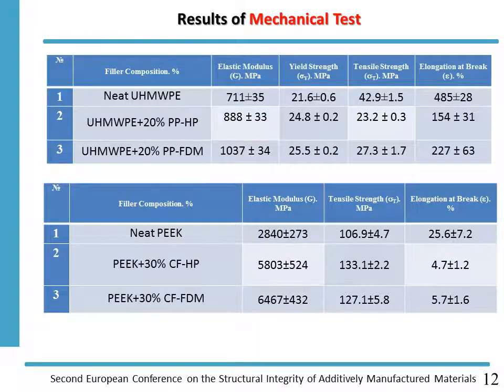The next slide illustrates the results of mechanical tests. What is of particular importance, first of all, for ultra high molecular weight polyethylene, is that with the use of fused deposition modeling we were able to increase significantly the elastic modulus. The yield strength is also higher in contrast with hot pressing, as are the tensile strength and the value of elongation at break. Most of these mechanical parameters are higher if we use fused deposition modeling for such a composite.